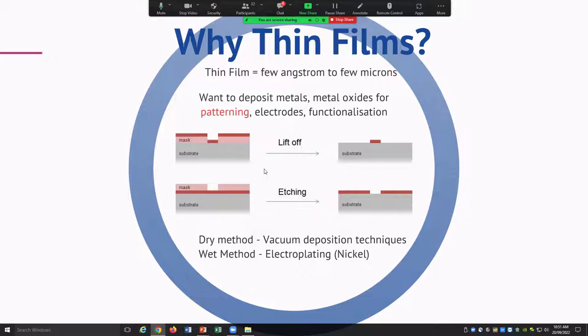So this is where the photolithography comes in. Coating is just a two-dimensional boring surface until you match it with photolithography and unlock a lot of the possibilities by photolithography. So you can pattern a mask, overcoat the mask, leave an electrode behind on your device, or vice versa. You can put your coating down, you put a patterned mask over the top, and then etch away to reveal a pattern as well.